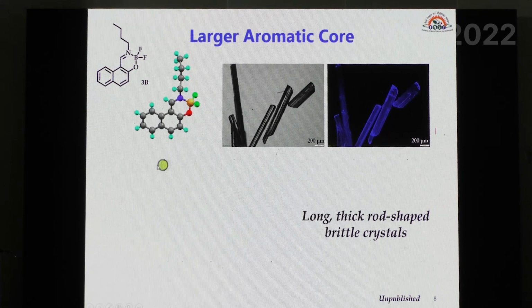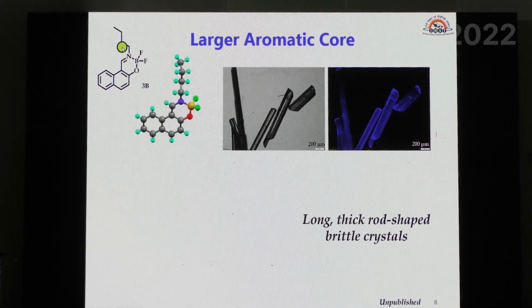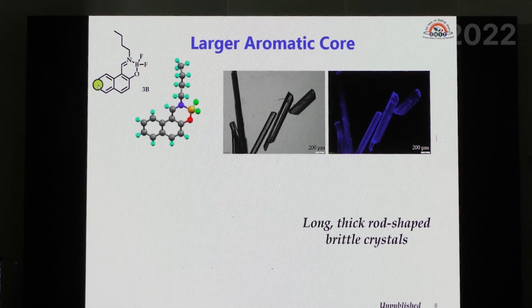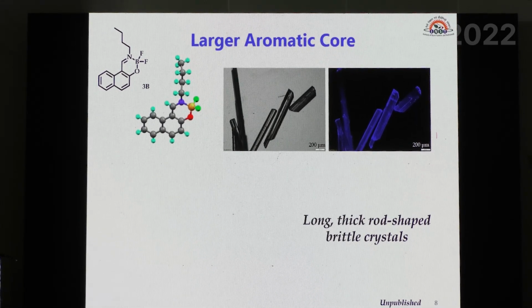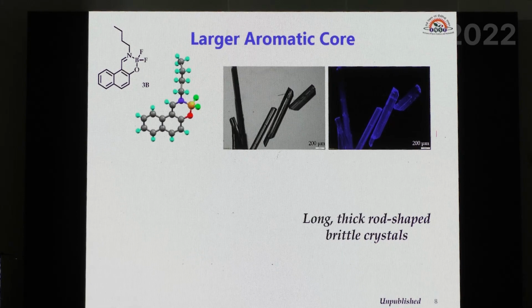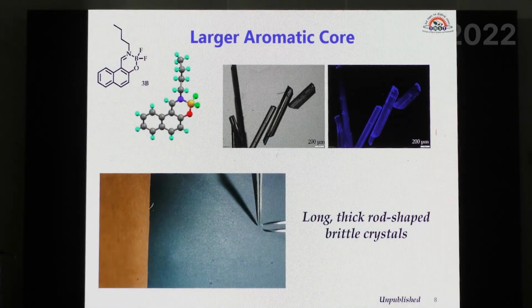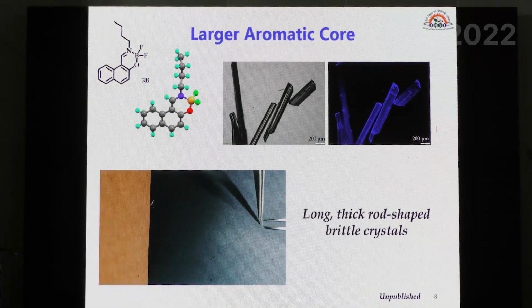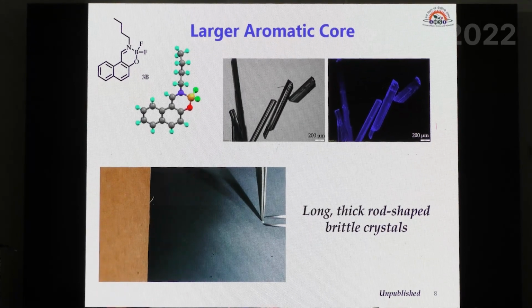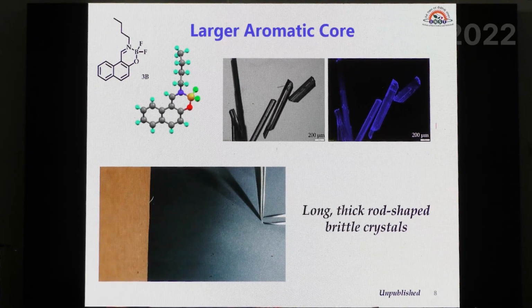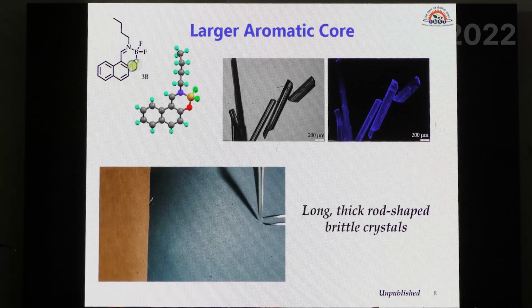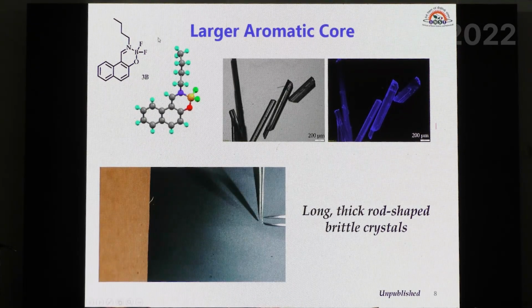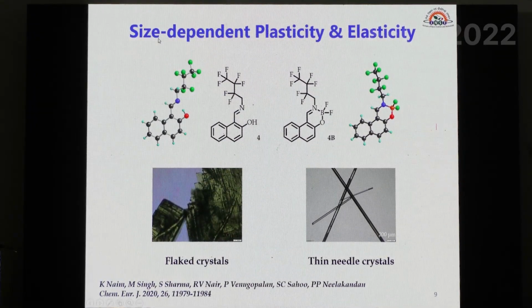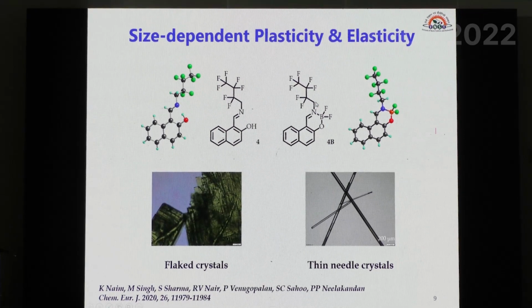We simply added one more aromatic ring here, but as soon as the number of rings increased, the nature of the crystals changed completely. Before we got much bigger crystals, and they were completely brittle. The moment you touch it, they simply break. They don't have any flexibility. So what we did, we retained this core, and we changed the alkyl chain into a fluoroalkyl chain, and these are the imines and their boron compounds.